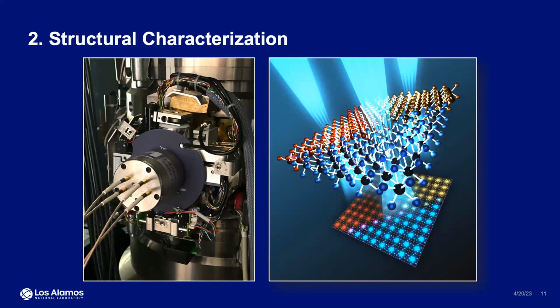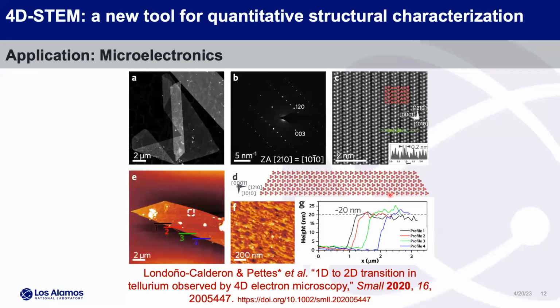We're still using 2D materials for this demonstration, but we hit it with a probe that's patterned. The nice thing you learn when you do a lot of electron microscopy work is you can tear things out and change things. So working with Berkeley, we changed the shape of the electron probe so it's not circular anymore. And you can hit the sample, diffract, and collect those diffraction patterns over a space to come up with grain statistics in 2D material. This 2D material is not exfoliated. It's grown by our collaborators in Korea on silicon dioxide. So it's not epitaxial. Grains are about 50 nanometers. So that's kind of the motivation for that. But I'll just show you some results.